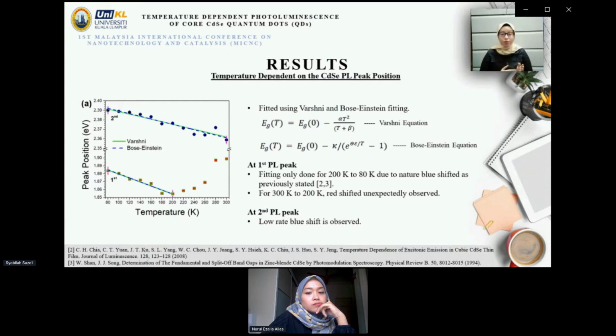As an alternative to provide a more accurate and precise result, Bose-Einstein fitting is used, as the error returned is much smaller compared to the Varshni fitting. This represents the strength of electron average phonon interaction. This is the Einstein temperature. This parameter corresponds to the acoustic phonon, which contributes to the bandgap redshift.